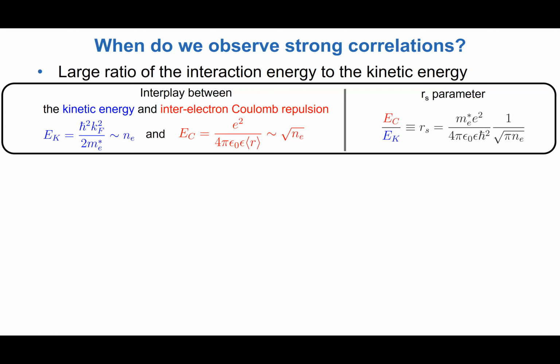So since these energy scales are going down, what is not in this comparison is the disorder energy scale, some random potential. And we want to avoid this. So we want to avoid that the disorder potential is the dominant energy scale. So one really seeks out a range of densities where the disorder is screened out, and yet interactions are much more important than the kinetic energy.